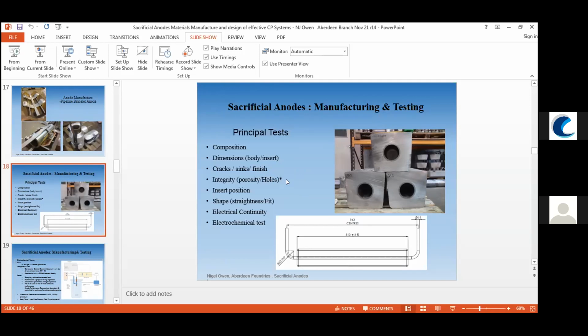And there are hundreds of configurations of anodes. It's unbelievable that we're casting anodes from say 1 kilo of aluminium to 450 kilos of aluminium. And they're on different sizes, widths, and they can be 3 meters long. So these can be monsters, and they can also be very difficult to control shrinkage, cracking, feeding, etc. as you're doing it. So this is why these checks are in place.